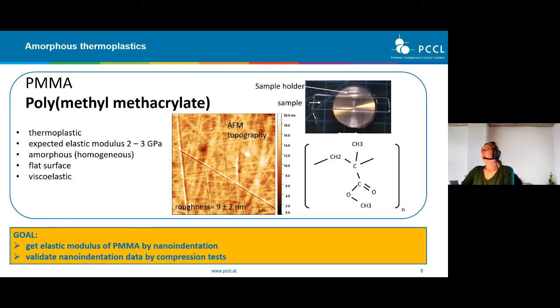You can see here the PMMA sample on the right side. PMMA is a thermoplastic, and it has an expected elastic modulus between 2 and 3 gigapascal. The sample here is amorphous and very homogeneous. It has a flat surface, and this is very important for nanoindentation. And of course, PMMA is viscoelastic. The goal of these investigations here is to get the elastic modulus of PMMA by nanoindentation and to validate this nanoindentation data by compression tests.